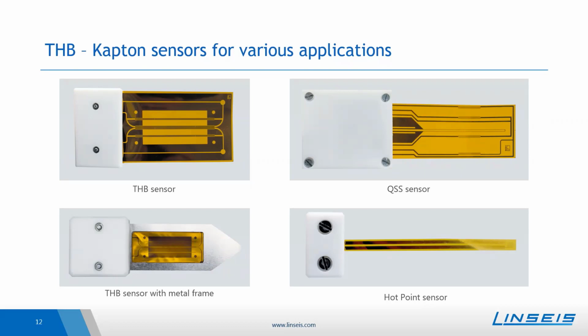Our next question, which came up, is how deep does the sensor heat the sample? So the sensor contains some heating wires within the THB sensor. This is more or less here, this region. For the QSS sensor here, you can see in the middle the heater and the resistances on the outside, which then measure the temperature increase with time. And these heating and measurement wires more or less heat up the sample to some millimeters. This is why the sample thickness should be higher compared to the penetration depth.